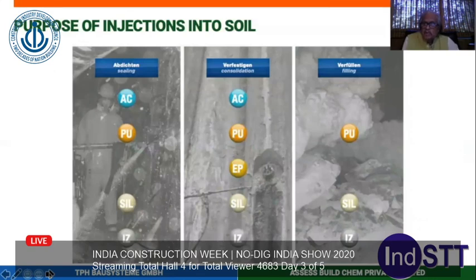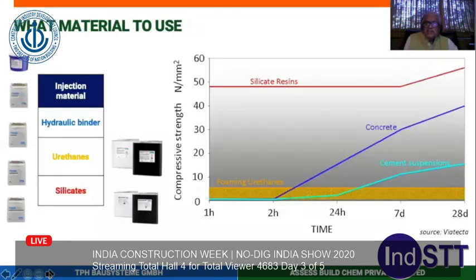Which can set in water, which can set without water, which can set in water or outside water. This is for the purpose of injection in soil. The reason I'm telling is, when you are doing this, these are the strengths developed. If you see cement suspensions, micro cement, it develops very, very little after 24 hours. The strength developed is not even 10 newtons. After 28 days, because you are putting so much water into the cement suspension, it's only 15.